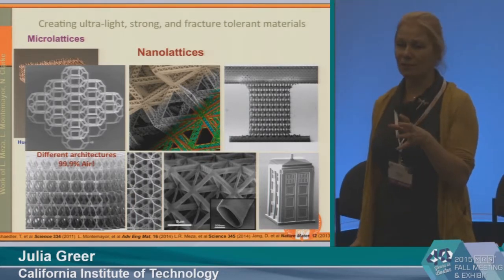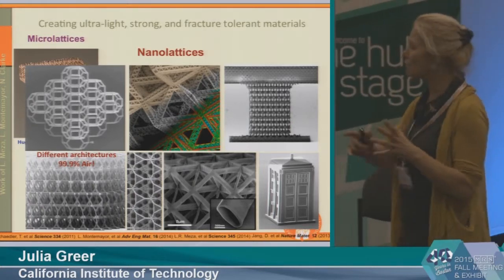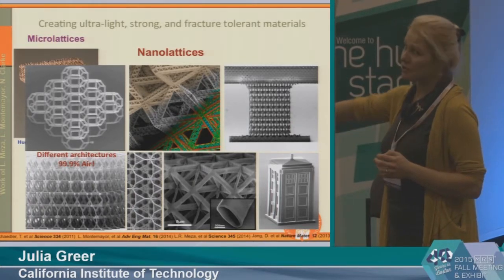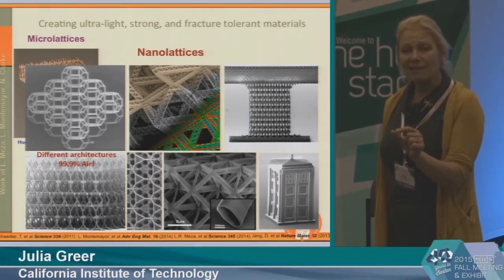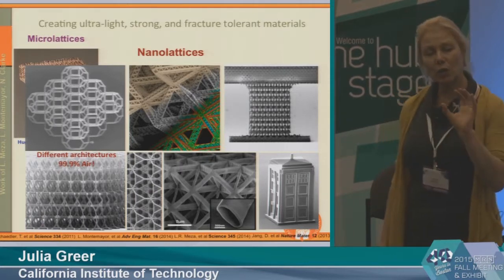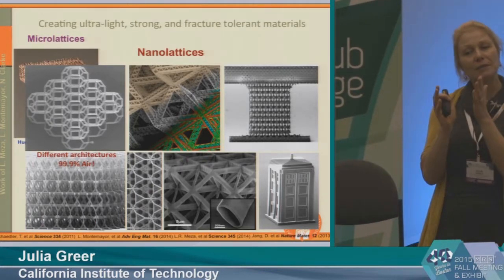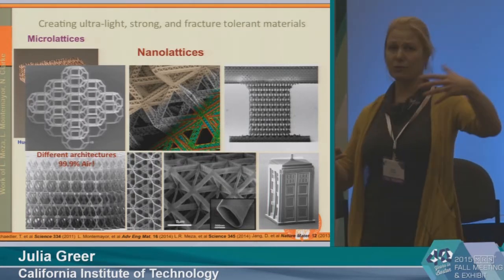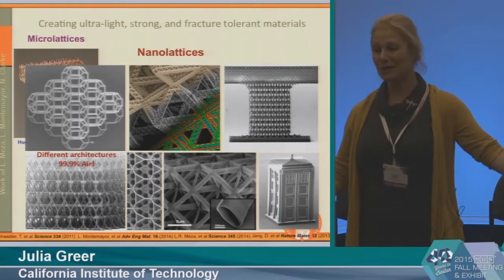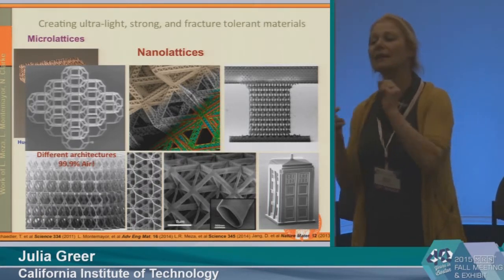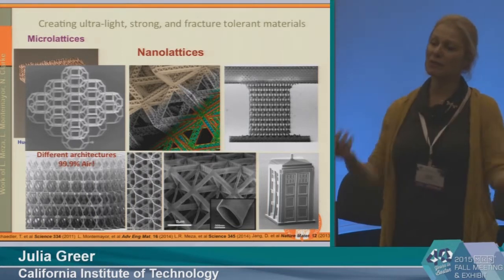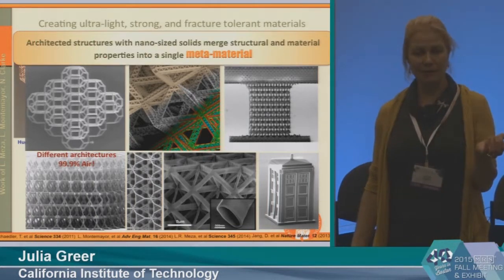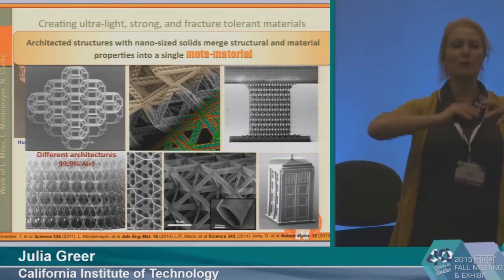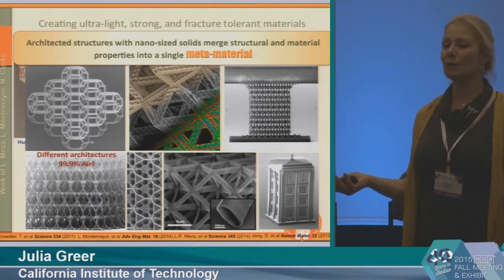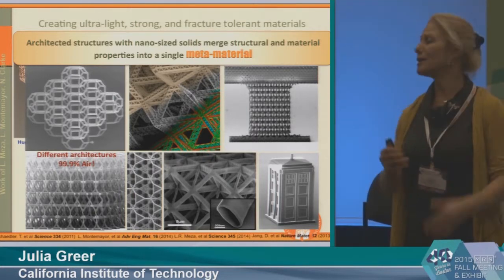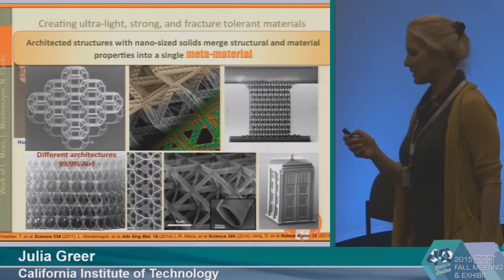And so this less obvious level of porosity comes from the fact that the tubes that comprise these nanolattices are all hollow. So here's a zoomed in image. And what you see is that each tube is hollow and the wall thickness can be on the order of 10 nanometers. Okay, so we're looking at a material that has every single length scale from 10 nanometers to maybe hundreds of nanometers to some microns to tens of microns and hundreds of microns, millimeters, and eventually centimeters. And so you can imagine that at every length scale, there are going to be unique properties that emerge. Because of that, we feel it's appropriate to call these materials metamaterials because their overall properties can no longer be described purely from the structural perspective or purely from the material perspective. They play together to define a new set of properties in these new nano-architected metamaterials.